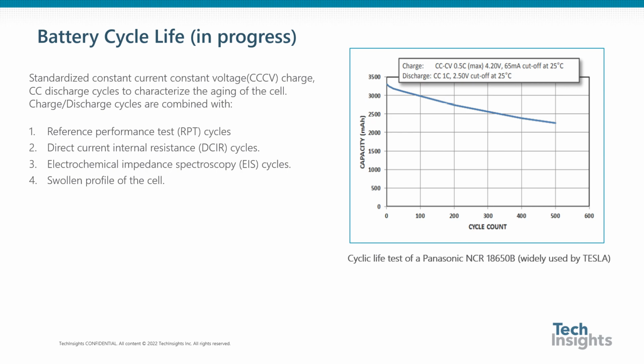It is possible that during the cycling of the cell, the soft pouch expands due to gas generation because of the side reactions. To track the cell swelling profile, X-ray images are taken every 100 cycles from different angles at least 6 sides of the battery in comparison to that at the beginning of the cycle life.